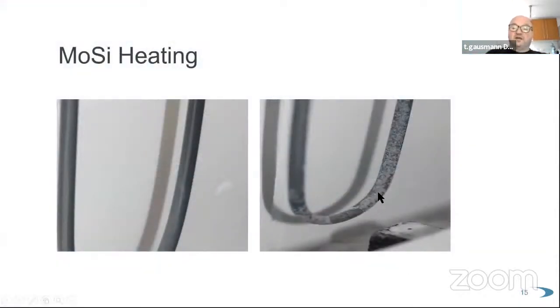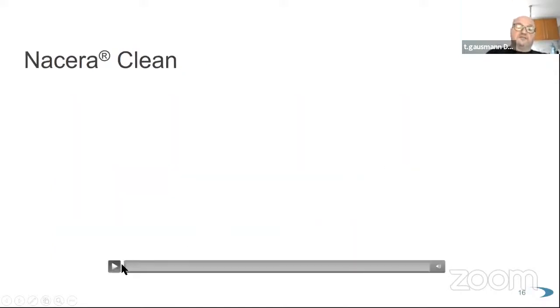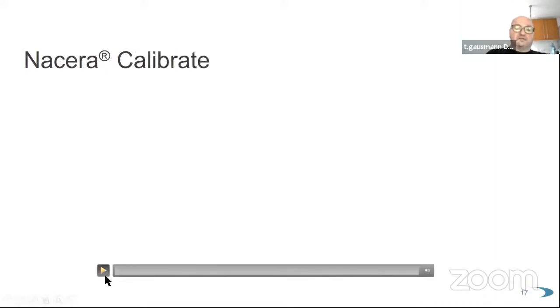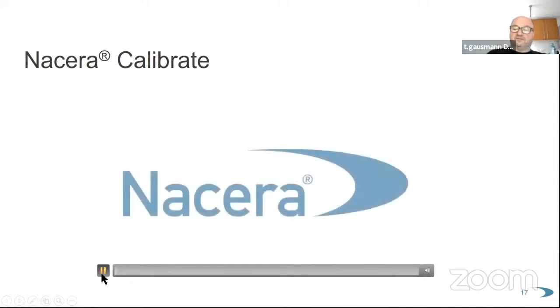So sometimes you've got a furnace with a molybdenum silicide or silicon heating. When it looks like this, this is no good, because this is silicon oxide on the surface. And this silicon oxide can lead to discoloration in the direction of yellow for the material. So it should look like this, silky, smooth, and gray. How to get this back? I tell you now. We've got something that is called Nacera Clean, and this is a small film. I just let it run. Hopefully it works.